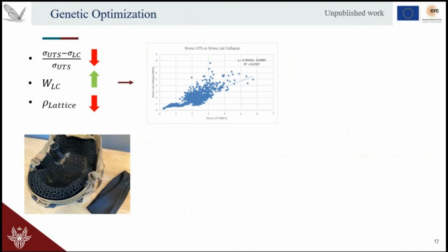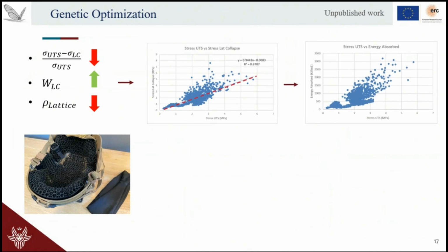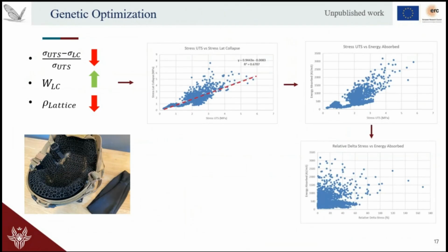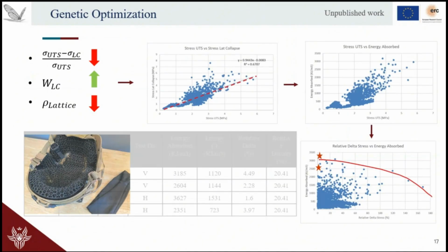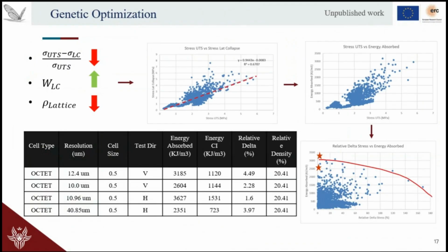For example, here there is a linear correlation between the UTS stress and the stress of lateral collapse, and that's good because we want this. It's the line. If we also see the correlation between ultimate tensile strength and energy absorbed, we see an almost linear correlation, but it's interesting looking at the relative delta stress and the energy absorption, because here we can trace the Pareto optimality frontier. We can choose our optimal points, they're just chosen by the user, and we can then choose the best print parameters for this case, for both vertical loading and the orthogonal loading. And those are the best parameters, and this is the energy absorption with its confidence interval.